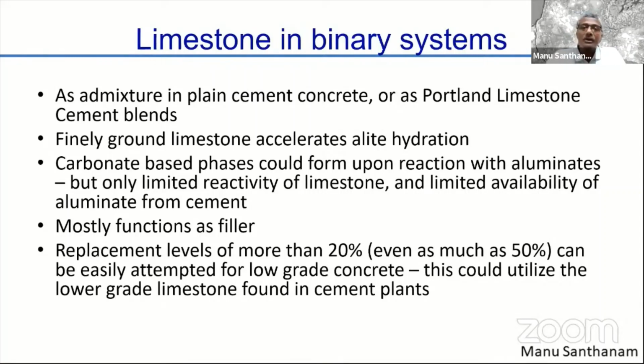As I said, in normal cement, it is already used up to 5%, but it's also used in Portland limestone cement blends wherever we have the possibilities as per the standards. The finely ground limestone, chemistry-wise, accelerates the hydration of your C3S or alite phase, and the carbonate contributed from the limestone has a chance to react to some extent with the aluminates given from the cementitious systems to produce carboaluminate-based phases.